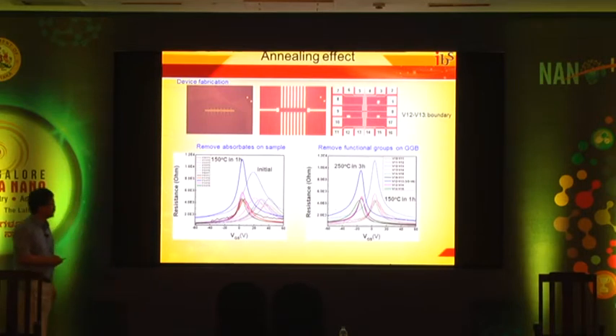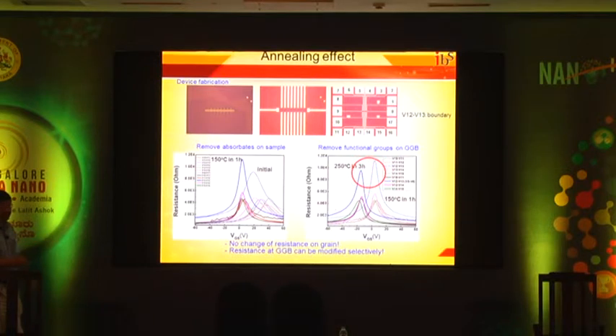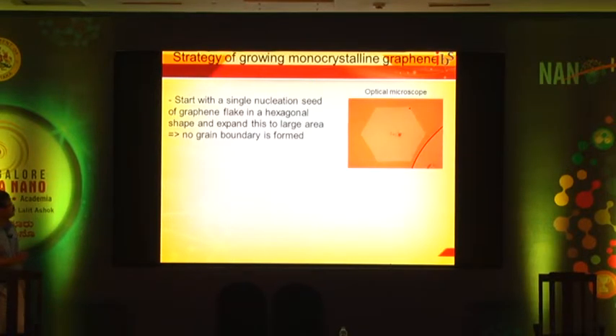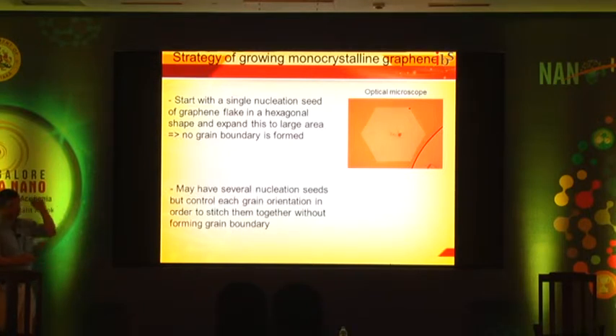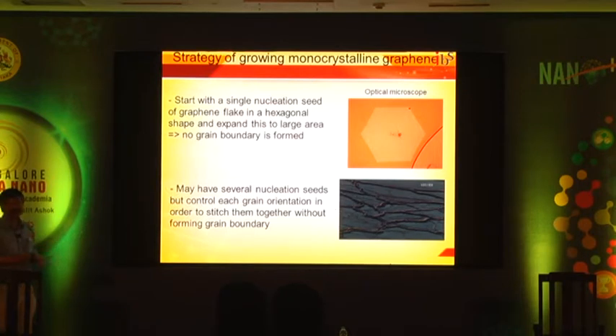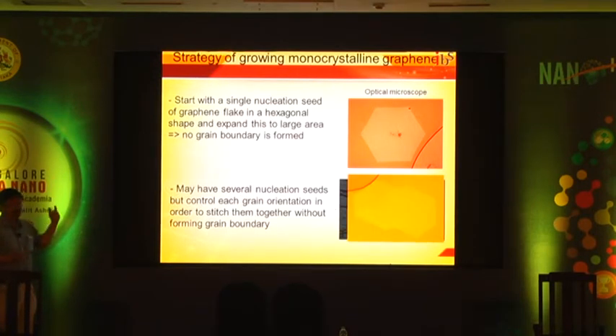So we confirm that this resistance is the intrinsic property of the grain boundary. Now, coming back to this issue, whether we can grow this large area graphene without grain boundary. Our approach: of course, if you start with a single nucleation seed, that will be very ideal, but it is very impractical. So we rather decide to choose multiple nucleation seeds, have a quick growth, and then remove this grain boundary.